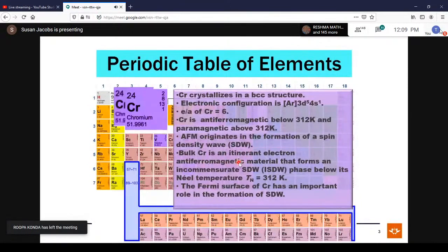Bulk chromium is an itinerant electron antiferromagnetic material that forms an incommensurate spin density wave, which we abbreviate as ISDW, below the Néel temperature, 312 Kelvin. Once again, I will explain what this is shortly. And in the formation of the spin density wave, the Fermi surface of chromium has a very important role to play.